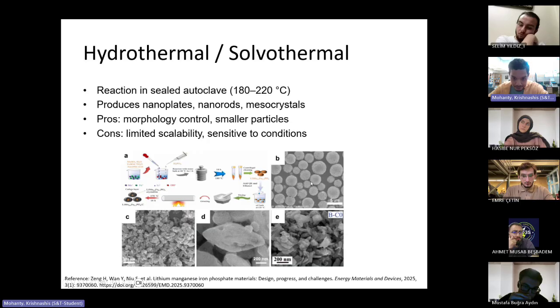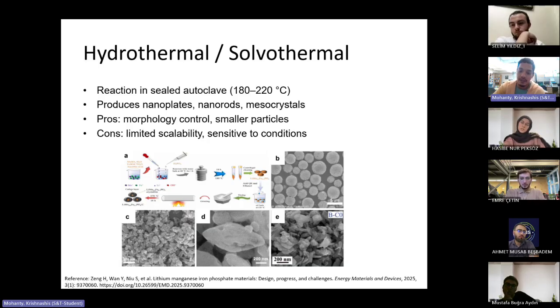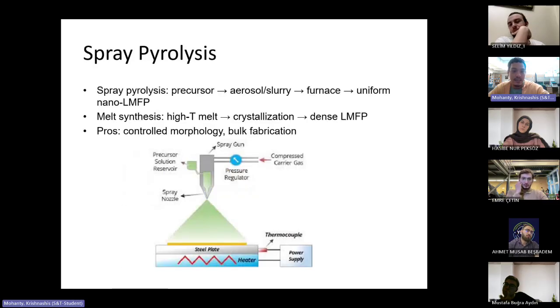As you can see here, this would be a general particle from a powder, LFP powder or LMFP powder, whereas C, D, and E are different shapes that you can morph your particle into. And because of this morphology, it also helps lithium ion diffusion. And lithium has much more area to be stored in as compared to normal particles. So quite interesting, you can morph shapes of particles.